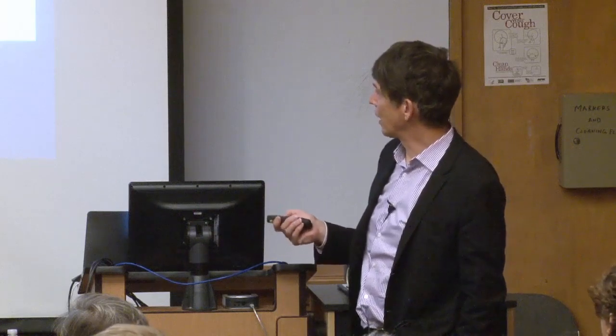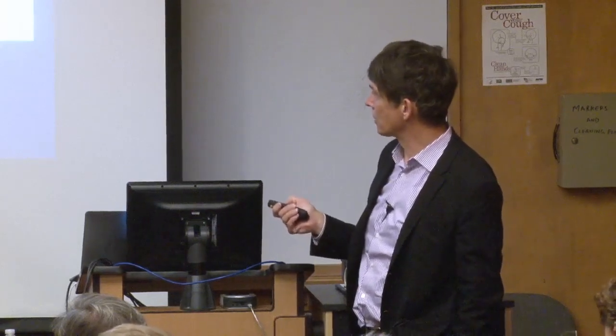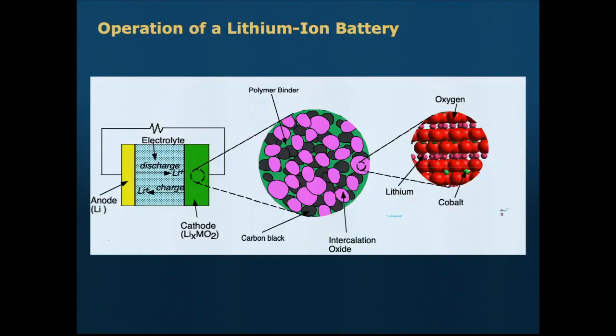So let me give you a very short primer on lithium-ion. It's essentially a shuttle device for lithium ions. You have an anode where lithium sits at high chemical potential. That's typically lithium in graphite today. And then you have a cathode where lithium sits at very low chemical potential. So if you remember your thermodynamics, the Nernst equation tells you that you can build up a voltage. That's the difference in chemical potentials. And for lithium ion, that difference is remarkable. It's close to 4, 4.5 volt, which, again, remember, water splitting is about 1.2 volt.